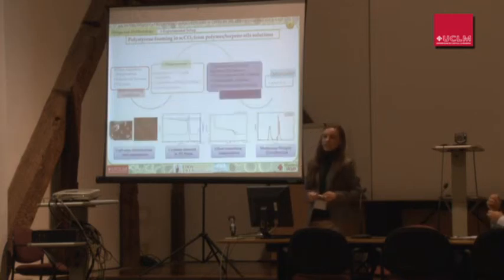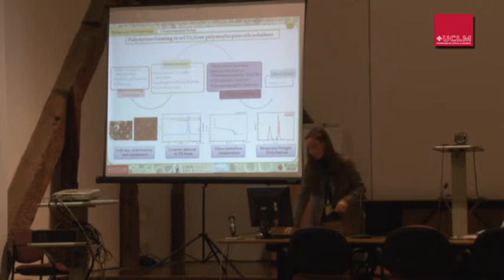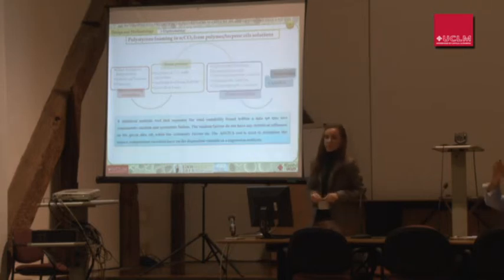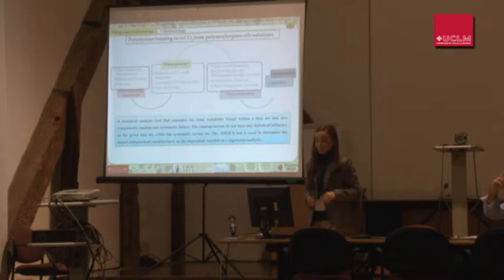The microcellular foam, our final product, was characterized by means of scanning electron and optical microscopy, and thermogravimetric analysis to determine the cymene or limonene amount. Calorimetric analysis was used to determine the glass transition temperature of the final product, and we also determined the molecular weight distribution by means of chromatographic analysis. Finally, a statistical analysis was carried out to determine the influence of the studied variables on the response.